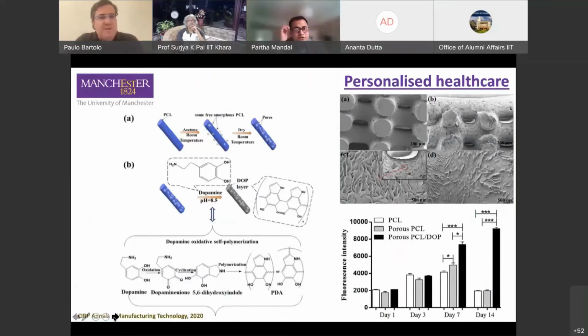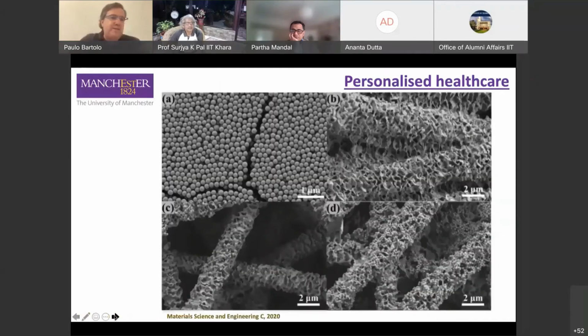To optimize the characteristics of these structures, we are developing different surface modification approaches. A few examples here. In this case, we use an acetone vapor annealing to induce some microporosity on the scaffolds, and then we dope the scaffolds with dopamine to improve the biological properties. Other strategies involve, for example, coating the scaffolds with nano silica particles, again improving the biological performance without compromising mechanical properties.